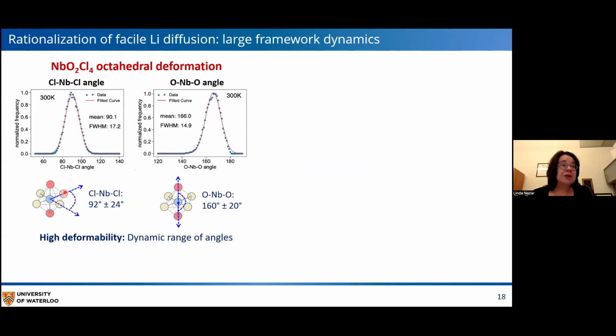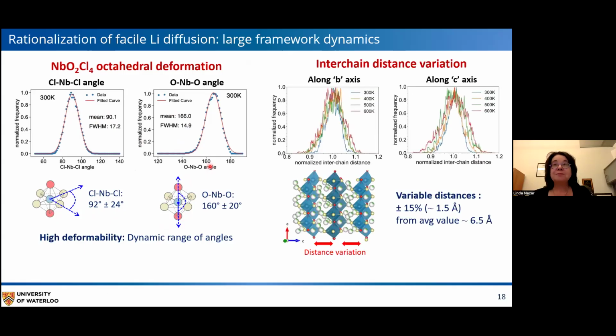And so you can see that the niobium chlorine angle is actually quite wobbly, it wobbles by about 24 degrees. So there's fluxionality in this plane. And also the niobium oxygen bond is wobbly, with a wobbliness in this direction by about 20 degrees. And this is shown at 300 K from our AIMD calculations. So we have a really dynamic range of angles, both for the niobium chlorine and the niobium oxygen.